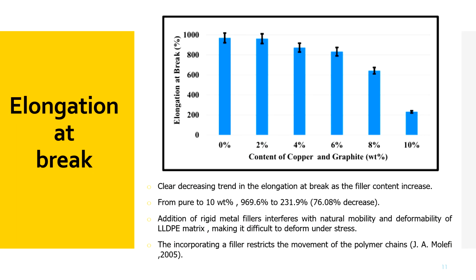However, when we look at the elongation at break, although we have seen improvement in terms of tensile strength, oppositely, the elongation at break decreased with the increasing of the filler content, as we can see in the graph above.